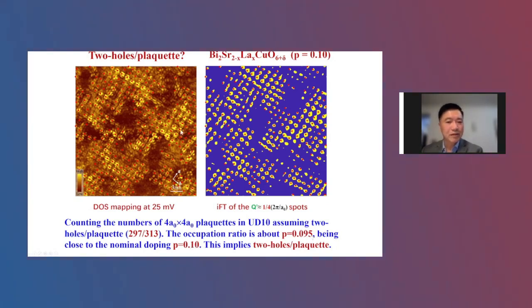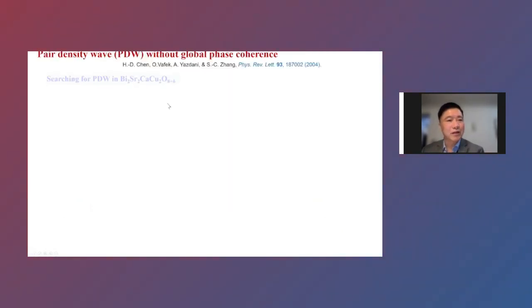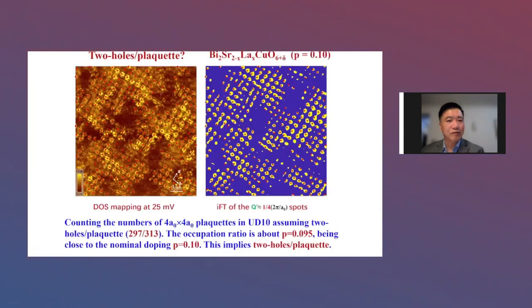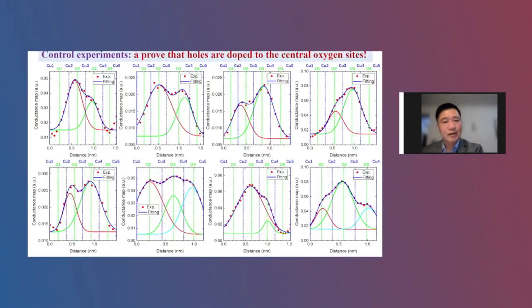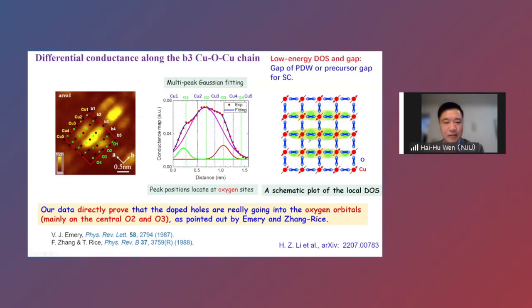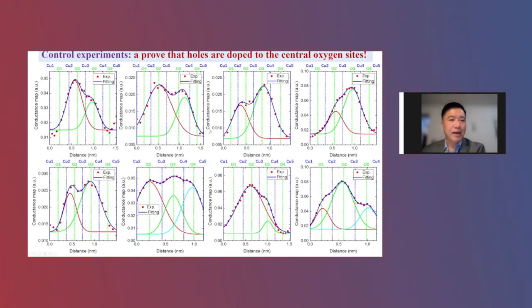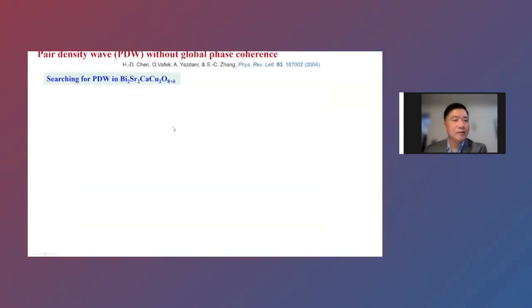So this slide shows that we probably have 2 holes doped to 1 block that form a pair, and that forms this kind of 4a by 4a, a very unique structure. Okay, so that's a basic pairing element. And for our 4a by 4a structure with internal nematic structure, one of the possibilities is that it is due to the pairing density wave, okay? And that one gives the low energy gap.